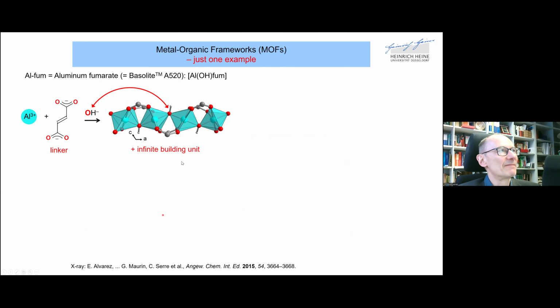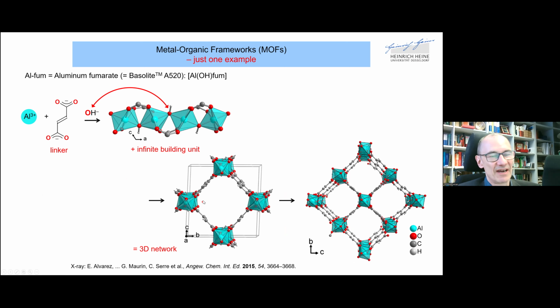So now let's come to aluminum fumarate, which I also introduced with that structure in the very beginning. It has these infinite building units, and from this, these square channel networks were constructed. So this MOF has a good stability and decent uptake capacity of a little bit above 0.3 gram per gram. So that brought us also to the field of aluminum MOFs.